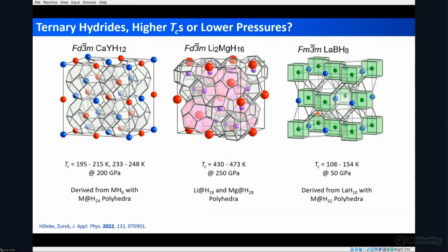And as mentioned by Julia, though we can reach very high TCs in some of these systems, it's only at high pressures, so we need to go to ternary or potentially quaternary hydrides because adding in these extra elements can give rise either to higher TCs, as has been predicted for the lithium-2 magnesium H16, so TCs above 400 Kelvin at 250 GPa, or to a lowering of the pressure at which superconductivity can occur.